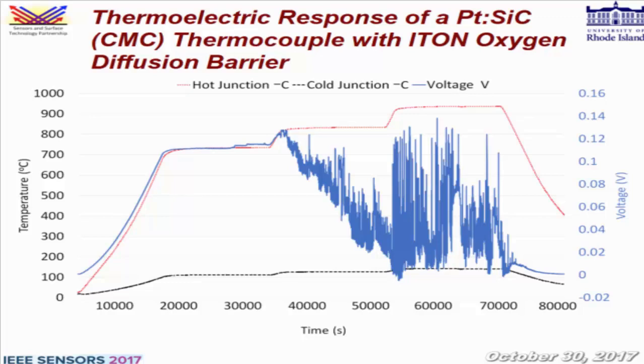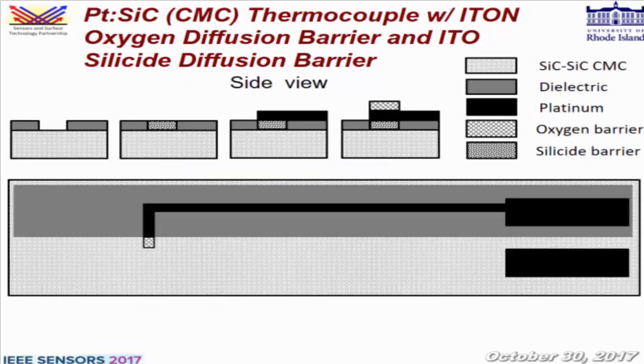A coating worked the first time, so why wouldn't it work the second time? And so that's what we did. We sputter coated a pre-coat of indium tin oxide. It's non-stoichiometric and it's very conductive. The reason we chose it is that we want to maintain an ohmic contact at this region.